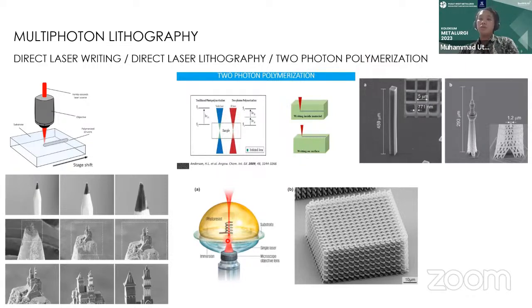we can use the SU8, so the material that we already discussed previously. So we can put SU8 on top of a substrate, and then we can have lasers coming from the top and bottom side of this photoresist, and then we can have the SU8 crosslink in specific voxels or points inside this three-dimensional space. So we can have this kind of structures. If you can see here, the length scale is 10 microns, and using this kind of technology, we can have these scaffolds, arrays of porous cubic structures, at this kind of scale.